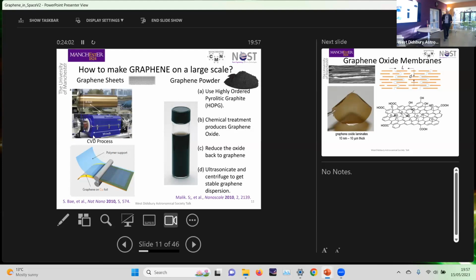And then if you want to do experiments on it, often we want to do electrical experiments, things like that. Well, it's on copper, which is a good conductor, so you don't really want it on copper. You want to put it on some other material. Well, you can actually remove it from the copper. There are various processes now. There's even a roll-to-roll process for doing it. Samsung sunk a lot of money into doing that because what they were interested in was flexible touch screens. Graphene is transparent and conductive. So this is exactly the material you need to put on a touch screen in order to put the electrodes in to work out where your finger is. And so essentially that's why Samsung were really interested in it.